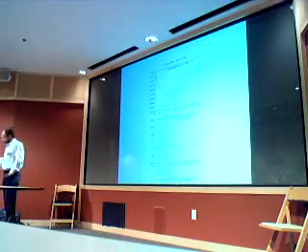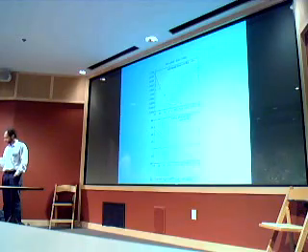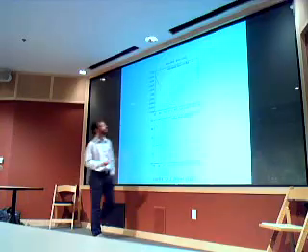So what's wrong? There is something wrong. What is wrong is not so much the stress, nor the particular energies that we are using, but the fact that if you were doing a calculation with many more points in the lattice parameter sweep, you would see that the function whose minimum we are trying to find is not very regular.